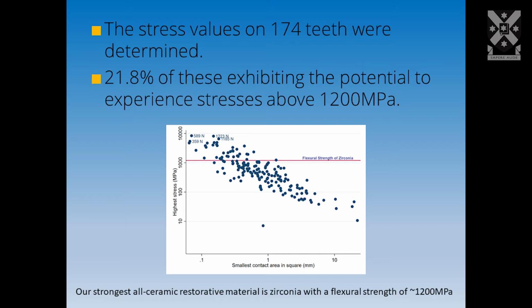21.8% were producing stresses above 1,200 megapascals. And the reason that that's a significant number is the strongest material that we use as an all-ceramic in restoring the mouth has a flexural strength of 1,200 megapascals, which is a stress value.